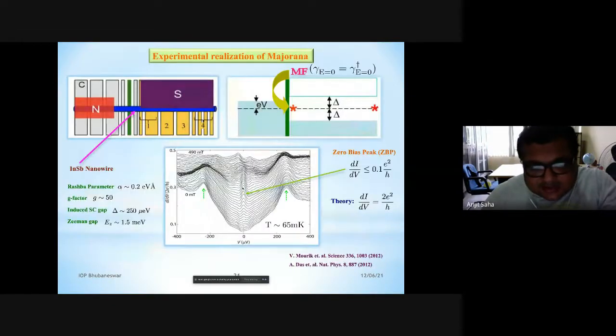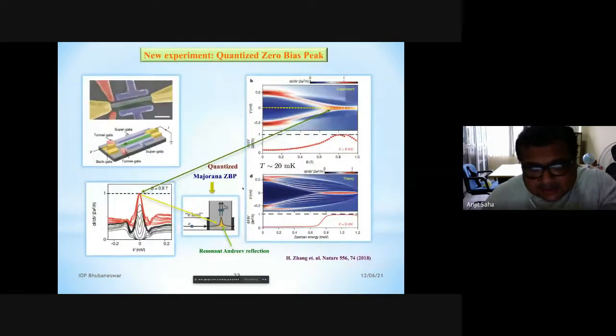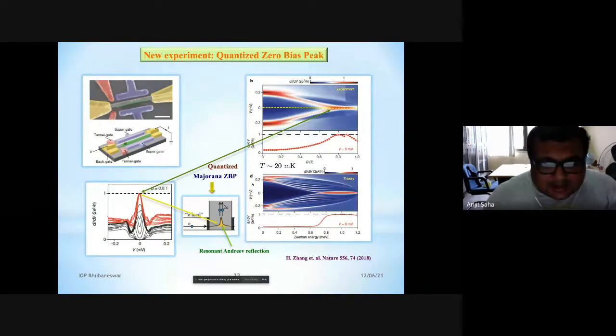So these are 3 experiments I am showing. This is a very recent experiment in the system, exactly what I showed you. They experimentally developed that, and they have shown, if you look at the tunneling conductance of this system, that they have chosen indium antimonide, which has strong spin orbit coupling, and as I have told, the Majorana appears at zero energy. So if you change the bias of your reservoir, at zero energy, due to the Majorana bound state, you have a quantized conductance of 2e squared over h.